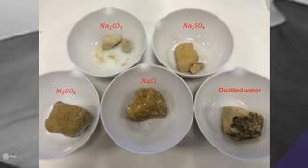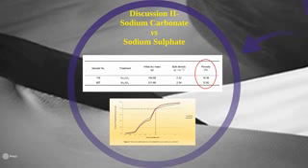As Cooke 1981 suggests, despite the nature of the salts involved, the properties of the rocks and the environmental conditions required to initiate salt weathering also determine the weathering effectiveness. Salts cause more damage to rocks containing a large proportion of micropores connected to macropores. Because thermodynamic assumptions are that salts growing in the macropores have lower free energy of formation and tend to be supplied with solution from the micropores.